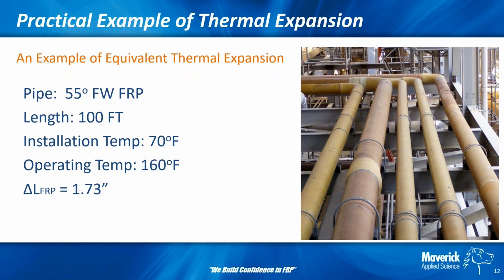So here's a general example. When we see systems operating at 160 in the FRP industry, to me that's an elevated temp. To somebody familiar with steel, they think 160 is pretty low. So we just do a quick example here of a 100-foot length of pipe based on a delta T of 90, 70 off of the installation, where 70 degrees is the installation temperature. You get a growth of almost 1 3/4 inches in that system.